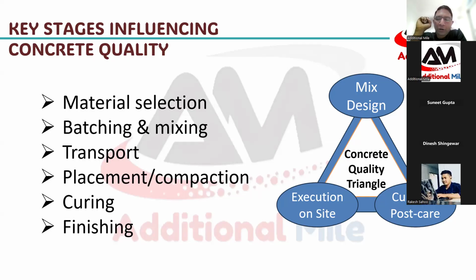If your concrete requires a good finish, then please design the concrete for that kind of finish, by going with a smaller size of aggregate. Don't use tamping or pressing on the concrete to pull the slurry up and finish it. The reason is you are disturbing the concrete bond mix. Second, once the slurry comes on the top, it becomes brittle.